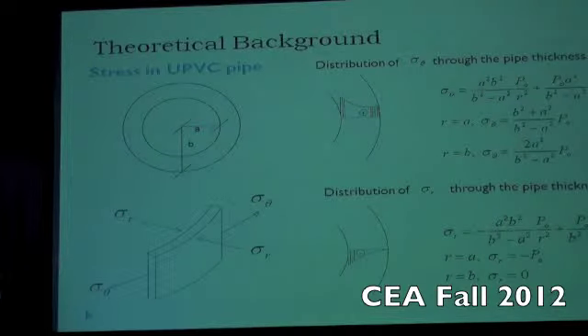For the tangential stress, it's a maximum at the inner radius, and then it reduces to a minimum at the maximum radius, which is b. As for the radial stress, it's zero at the edge of the tube, because nothing is in contact with the edge of the tube, and it increases at the inner radius.